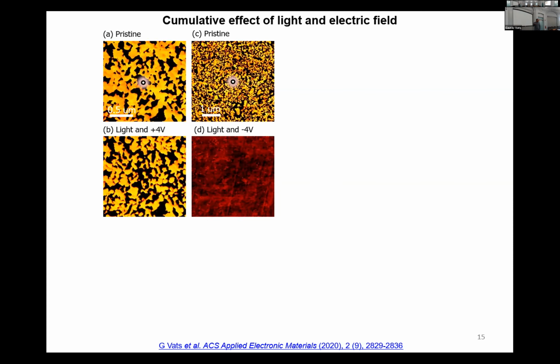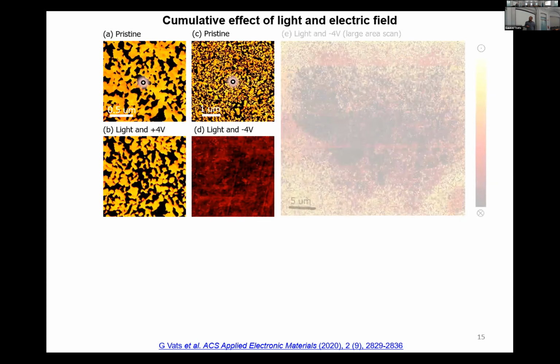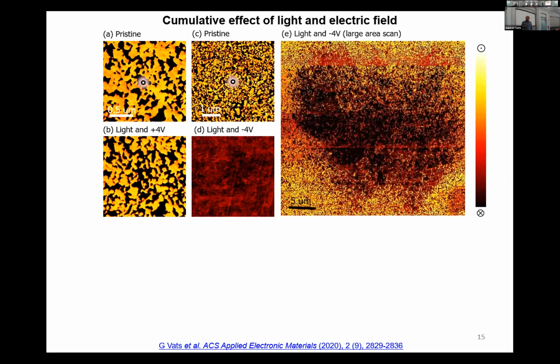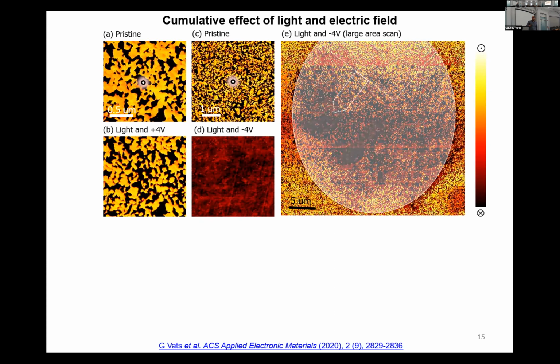And I was wondering how big this change could be. I scanned the nearby area. Again, the scale is different here. It's around 30 by 30 microns. And I got this weird shape. I repeated this measurement again and again with different light intensities and electric fields, and I got different kinds of shapes. And I was thinking what exactly is happening here. At the end, I was able to figure out that my AFM tip was somewhere here, and this was the laser spot size.